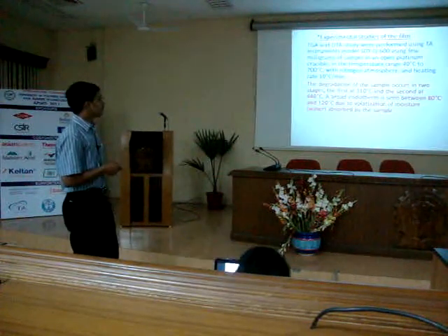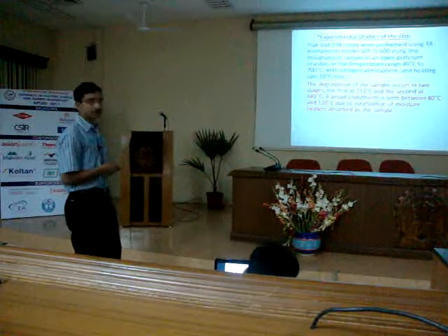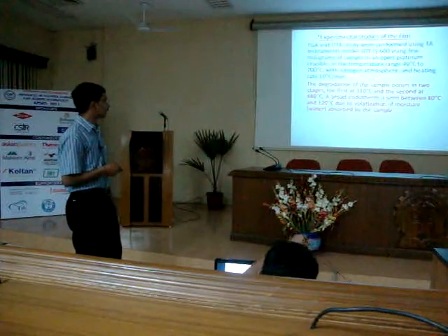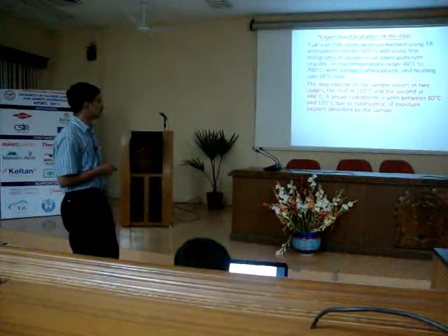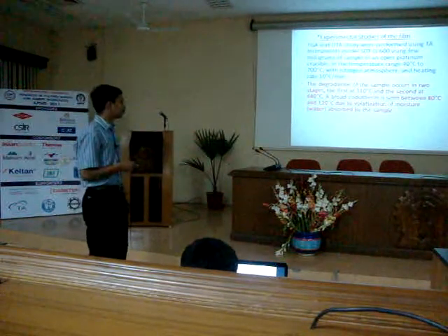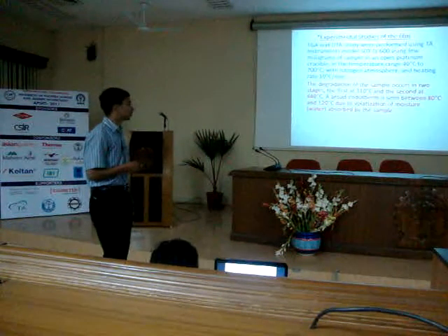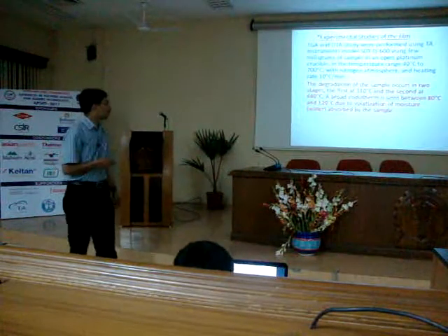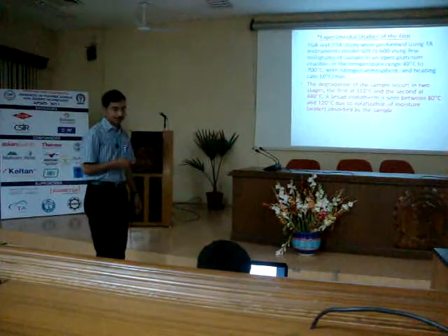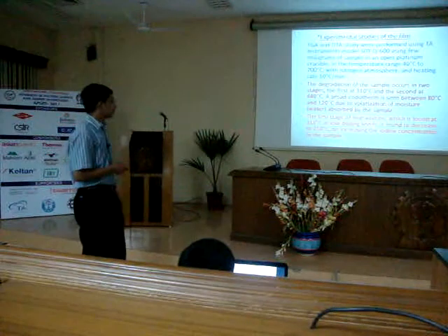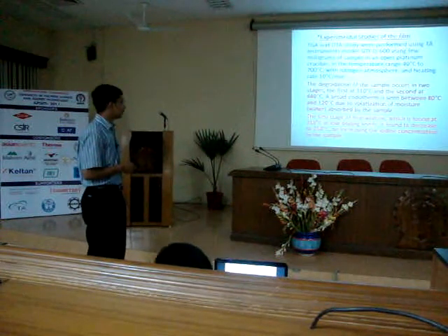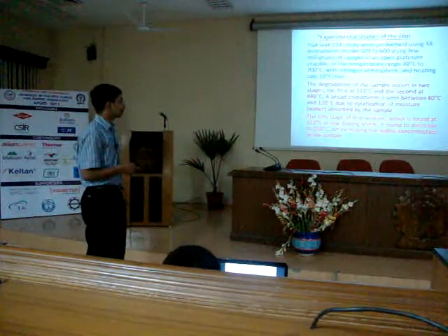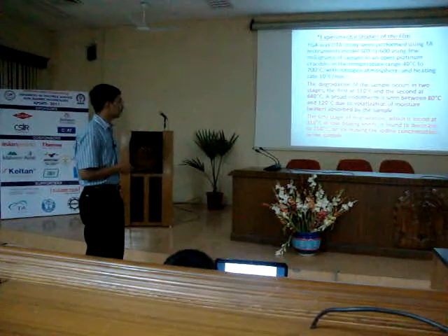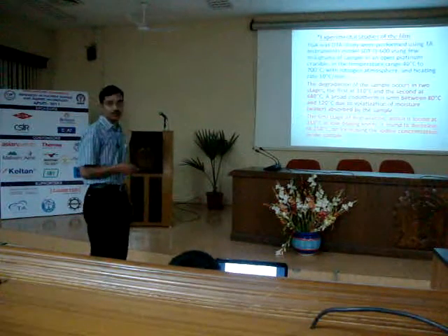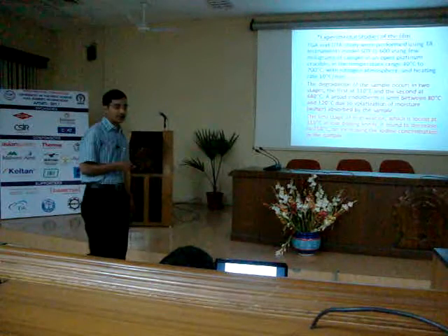The degradation of the sample occurs in two stages, the first at 310 degrees Celsius and the second at 440 degrees Celsius. A broad endotherm is seen between 80 degrees Celsius and 120 degrees Celsius due to volatilization of moisture absorbed by the sample. The first stage of the degradation, which is found at 310 degrees Celsius at low doping levels, is found to decrease to 250 degrees Celsius on increasing the iodine concentration in the sample.